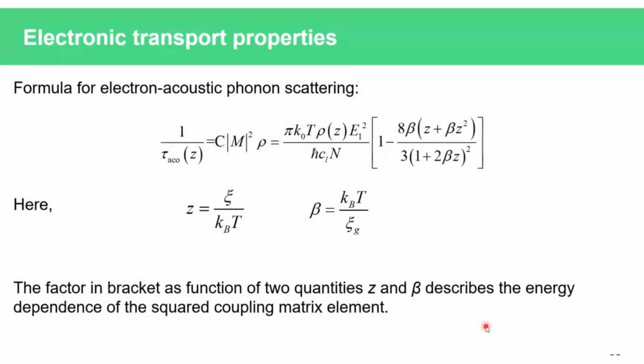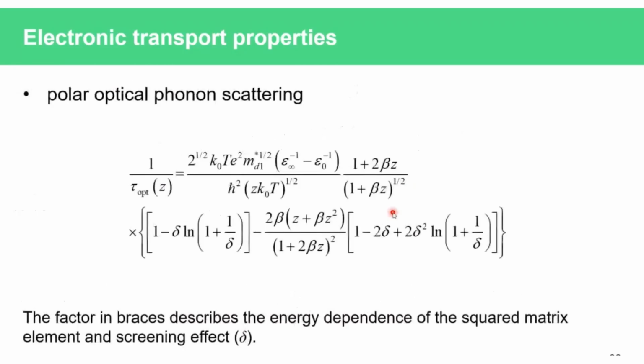Based on this Kane band model, the deformation potential theory can be expanded, and the scattering rate for electron-acoustic phonon is like this. Here, E1 is a deformation potential constant, CL is a direction-averaged elastic constant. The part outside the bracket is the same as the formula proposed by Bardeen. The part in the bracket is a function of Z and beta, describing the energy dependence of the squared coupling matrix element — its correction to the parabolic band model.